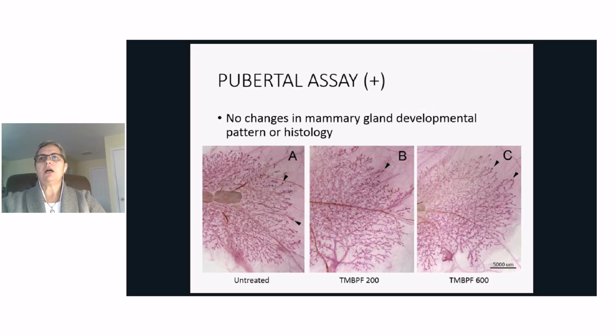We looked at the treated animals, you can see in the middle and the right panel, and compared them with untreated animals. We didn't see any changes in the developmental pattern of the mammary gland. So this led us to conclude that in both animal studies, TMBPF did not show estrogenic activity.